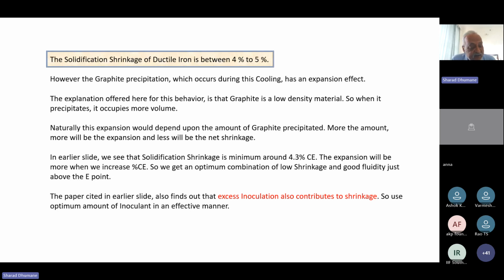Okay, so the paper cited in the last slide also found out that excess inoculation contributes to shrinkage. So now we saw that the chemical composition significantly impacts the solidification shrinkage. Now, same paper, when they were carrying out those experiments and collecting data, they also found out that excess inoculation also contributes to shrinkage. What it does and how it does, we will look at later. But it is good to keep in mind that our inoculation should be optimum. It should not be less, but even more also is not really advisable. So use optimum amount of inoculant in an effective manner.